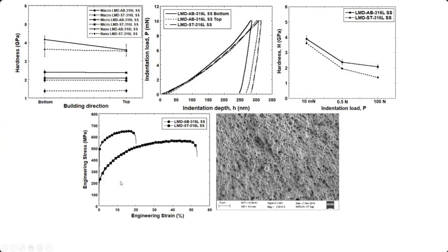Interestingly, it has been seen - this is the as-built structure, these circular points are the as-built tensile strength - that although the ultimate tensile strength or yield strength is higher in this case, if we use a solutionized additively manufactured material, there is a huge rise in ductility. It has more than 50% strain to failure, which leads to higher toughness of the material also.